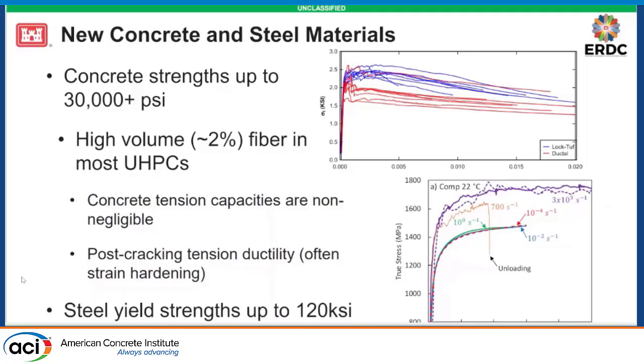So finally, looking also at steels, we have some steels with yield strengths up to 120,000 PSI. There's very little data in the literature so far on how these materials perform at higher strain rates, which is a limitation to them being used in blast design. I do show over here on the right some of the only data that I was able to find, and it's a little bit problematic for us civil engineers because it's presented in terms of true stress, true strain, and none of us like true stress, true strain.